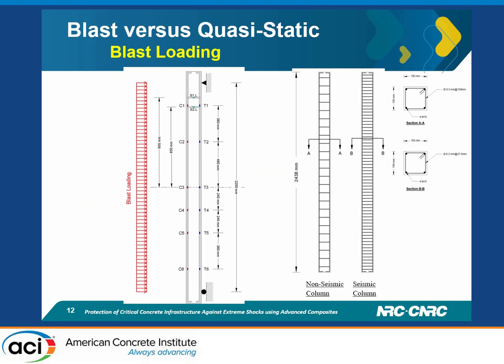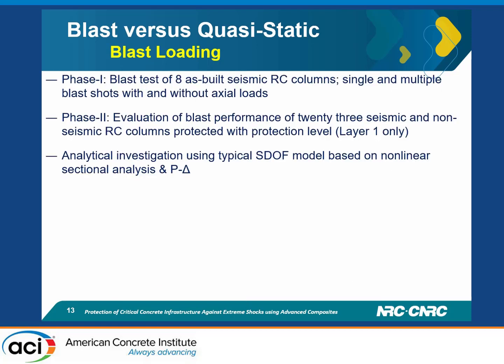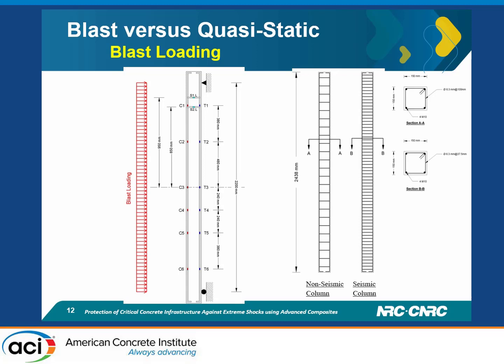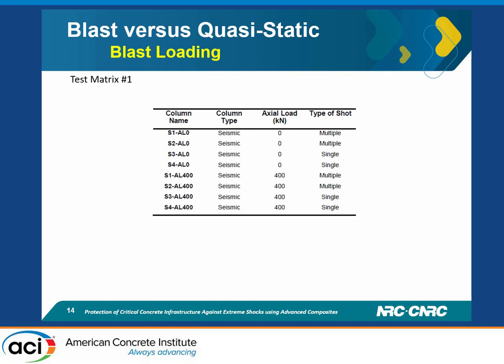For the experimental part of this study, we have a column with a size of 6 by 6 inch, 150 by 150 millimeter in section, and a height of around 2.4 meters. We selected a pin-roller boundary condition in the lateral direction, while applying an axial load of up to 40% of the full capacity of the column. We monitor the lateral reaction and also the change in the axial force during the test. We use very advanced monitoring technologies, monitoring up to 1 million data points per second per channel.